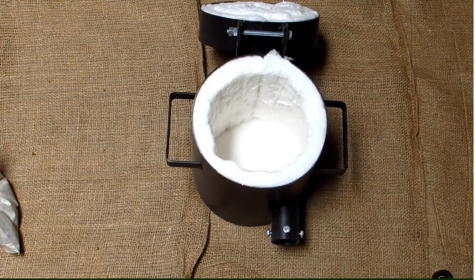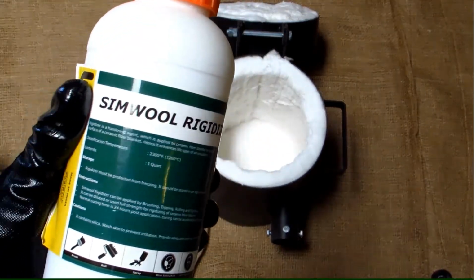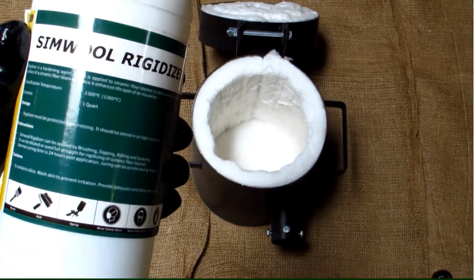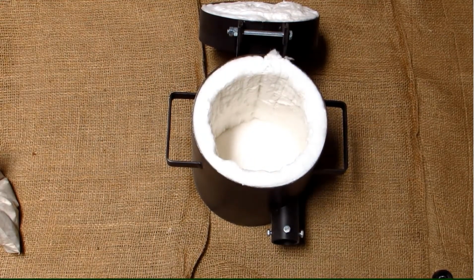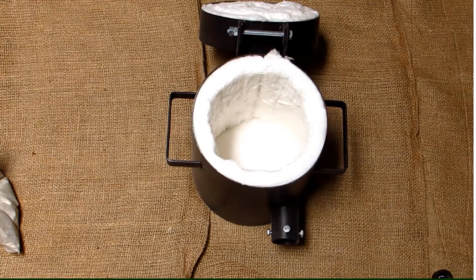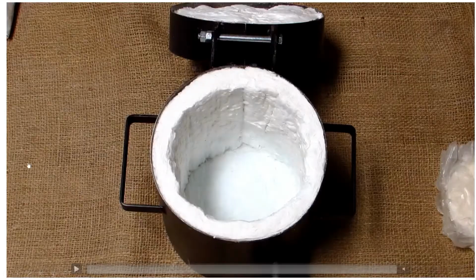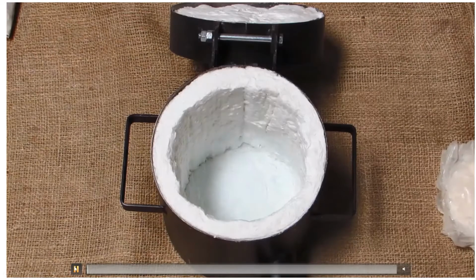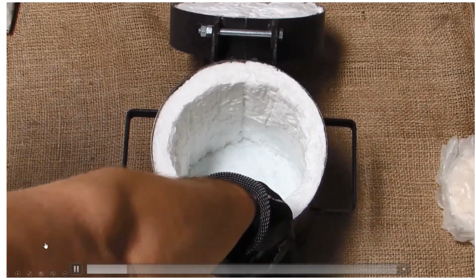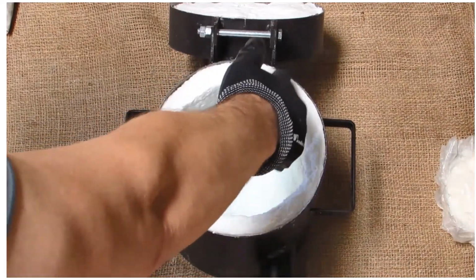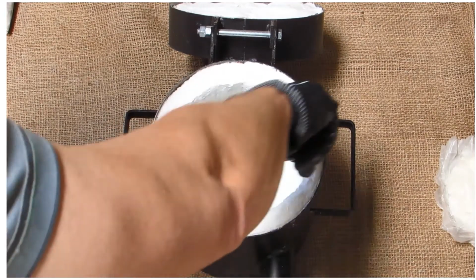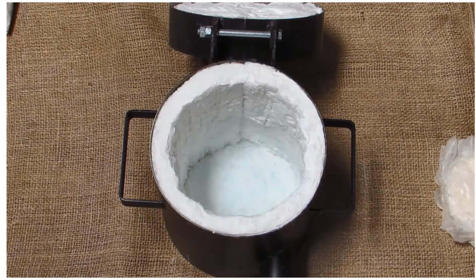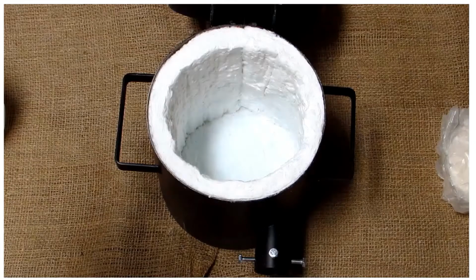So what I did first was I got this stuff called Simwool Rigidizer, and it's basically colloidal silica. And I put it in a squirt bottle and just sprayed the inside liner of my furnace. And we'll take a look at how that came out. After about 2 days curing in my garage at about 100 degrees, actually, the rigidizer had rigidized the ceramic wool. You can tell by touching it, it's a lot harder than it was, and that's pretty much what I wanted. I didn't want a soft surface to put the mortar on.